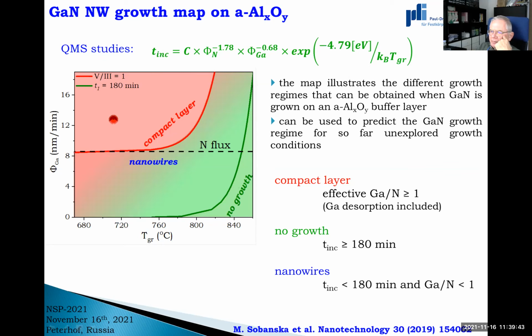Now, how to grow a compact layer? In contrast to the growth of nanowires, if we want to grow compact gallium nitride layers in plasma-assisted MBE, we need an effective gallium to nitrogen flux ratio of 1 or larger than 1. Effective meaning not impinging fluxes, but real fluxes, the real amount of gallium existing on the surface. So quite independently, we measured gallium desorption as a function of temperature from nanowire arrays. I'm not showing these results. This condition gives us this boundary.